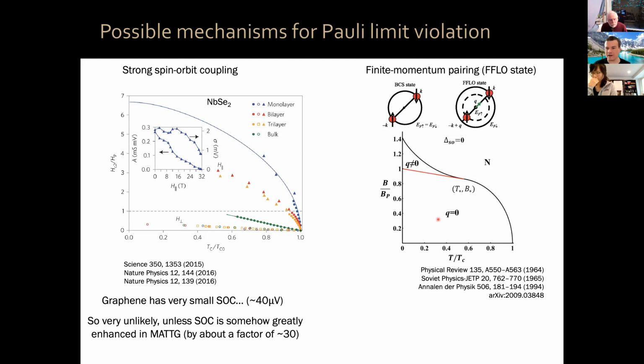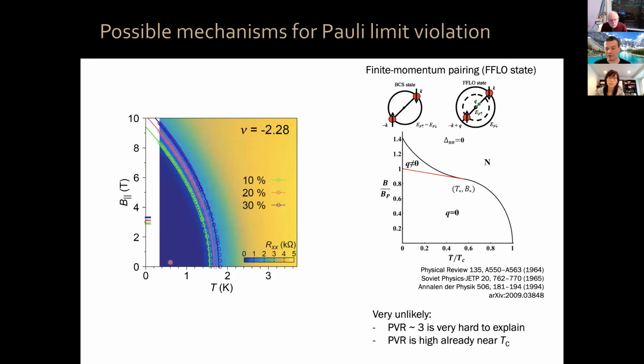Another possibility is finite momentum pairing, FFLO states, okay? In those cases, those superconductors, which are only a few that realize this, okay? You can have an enhancement of your critical field above the Pauli limit of order 20–40% at low temperatures, below half of TC, okay? This again is very unlikely in our case, because first of all, we see an enhancement of 300%, not 20%, okay? And in addition, our Pauli limit is violated right away from TC, starting from TC, okay? Not only at very low temperatures, but right away, we violate the Pauli limit, okay?